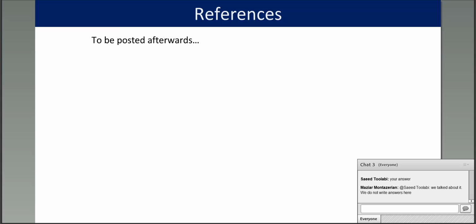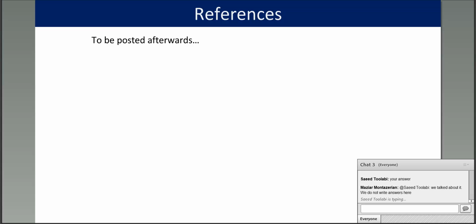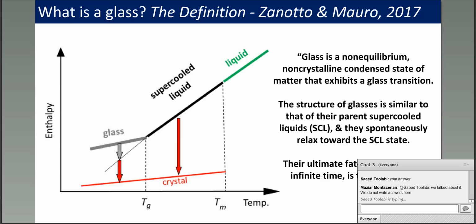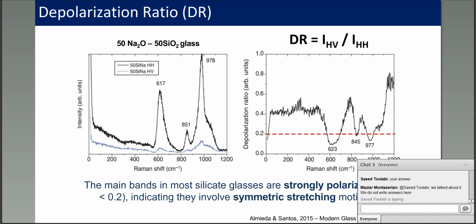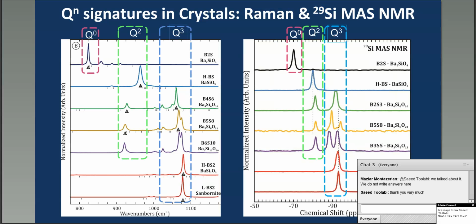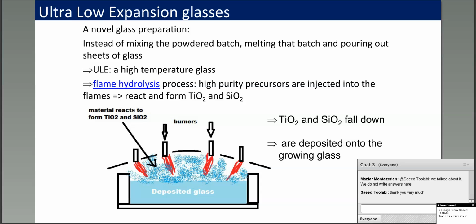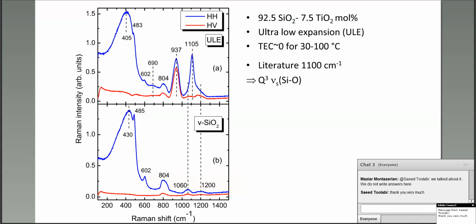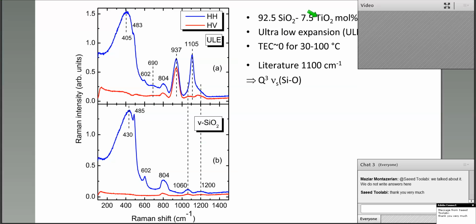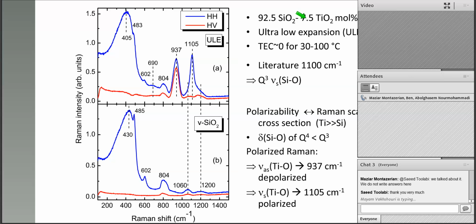But there's other things, for example, titanium. If you add titanium to the glass, the polarizability of titanium is huge. So even with 4 or 5% titanium or less, down to 0.5%, you get quite a strong band. Here's an example spectra with titanium. In this case it's only 7% titanium, and even with just 7%, you're getting a huge peak here that's almost as intense as the silica bands. So you can track this down to quite low concentrations.